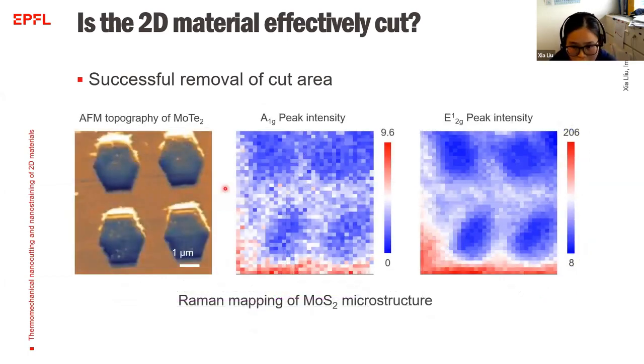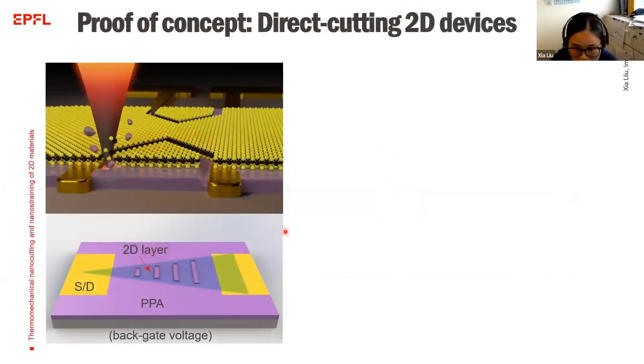We also have a further verification method provided by the Raman mapping. Here you can see I patterned a microstructure on the one layer MoS2, and the Raman pattern corresponds to the AFM topography. You can see here the intensity is much lower than in the red area. It means in this area, the 2D material is removed successfully. So we have developed this technique.